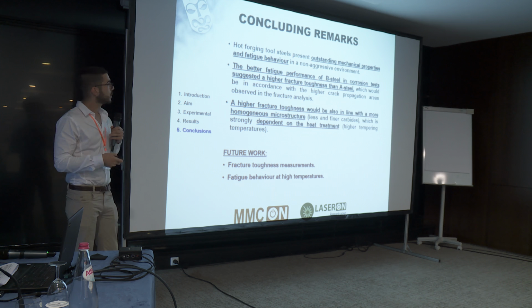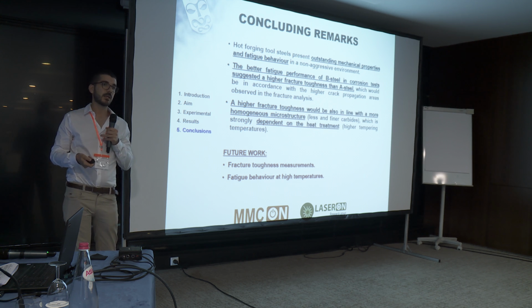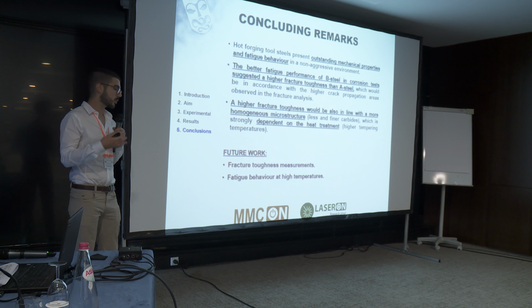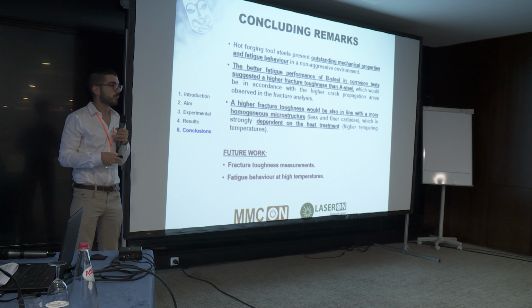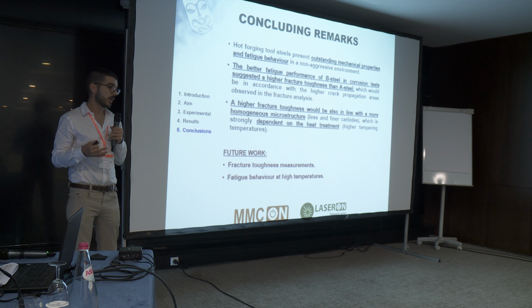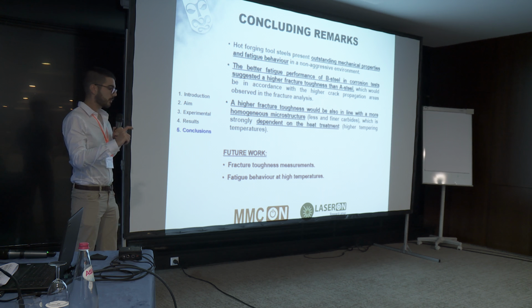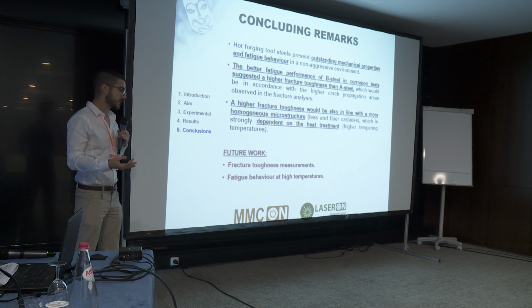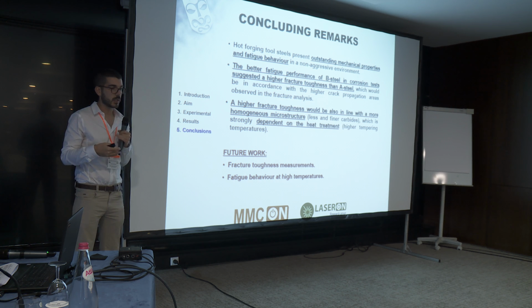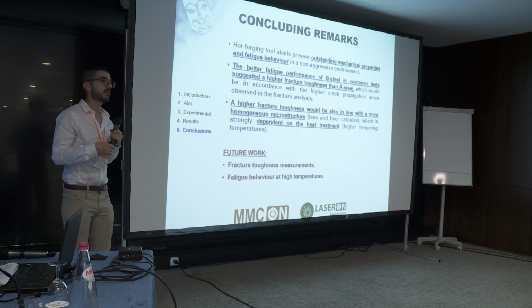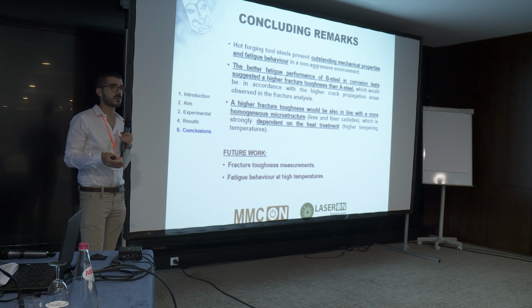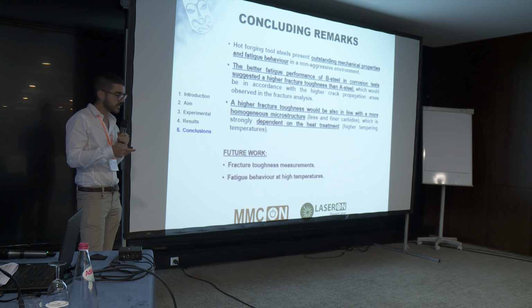And just to conclude the presentation, we saw that this family of steels, hot forging tool steels, present outstanding mechanical properties and pretty good fatigue behavior under normal conditions. Through corrosion fatigue tests especially, looking at the crack propagation areas, they suggested that B steel may have presented higher fracture toughness, probably due to the higher tempering temperatures and the finer microstructure that we saw, because it had smaller carbide sizes.